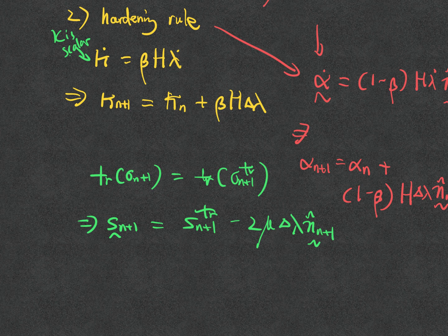Yes. I just want to put a little bit of pressure. Let me say it again. The trial deviatoric stress and the deviatoric stress are always separated by the correction, because J2 plasticity is sensitive to the deviatoric stress. But the mean pressure should contribute only with elasticity, right?